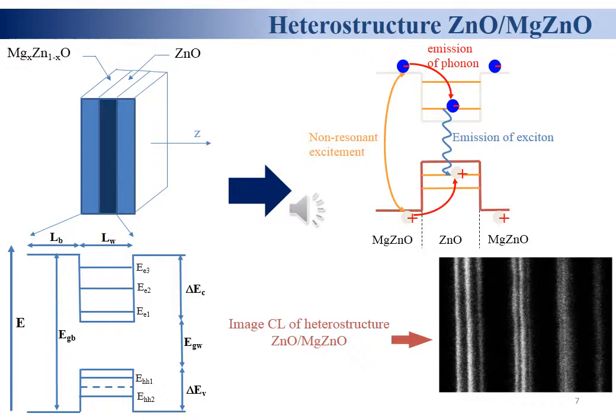We use the ZnO material as an active zone in the quantum well. The transmittance coefficient was then calculated as a function of the magnesium fraction, the width of the active zone, and the optimum value of the width of the well. The transmission coefficient is calculated using the finite difference method by considering the parabolic and the non-parabolic model of the conduction band.